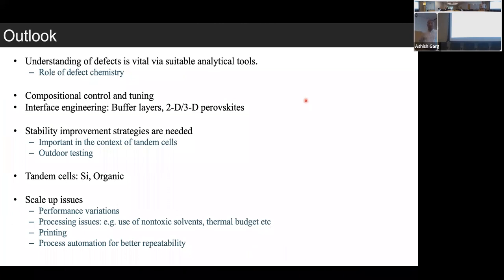So there are still a lot of things. For example, people don't really understand the defect chemistry in these, and often I have seen that defect chemistry people get it totally wrong, because they are not familiar with what is a p-type oxide, what is an n-type oxide, what should be the compensating defects. So I have seen perovskite literature which often has not very accurate models of explaining the change in behavior when you process certain oxides. So the role of defect chemistry is not yet very well understood. And also compositional control, tuning of interfaces, adding buffer layers, mixing 2D, 3D perovskites. It is something which is still very important.